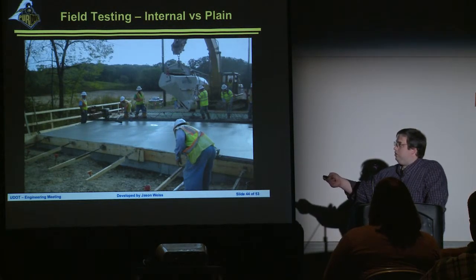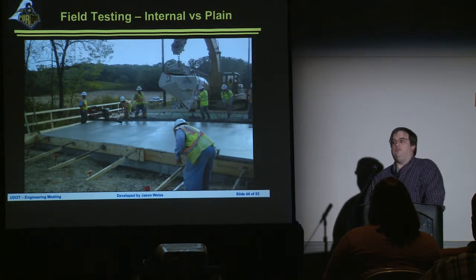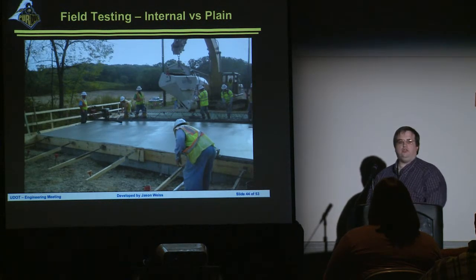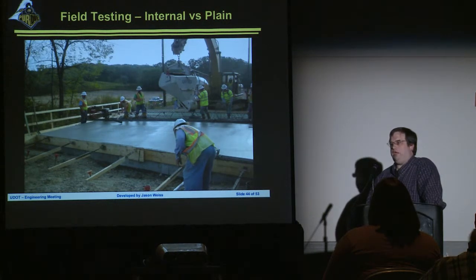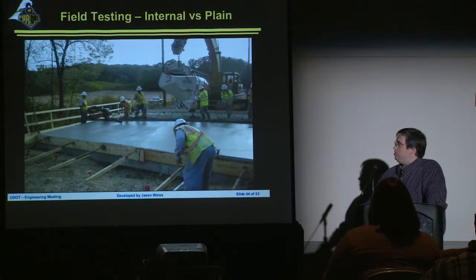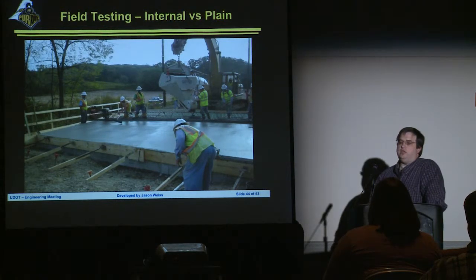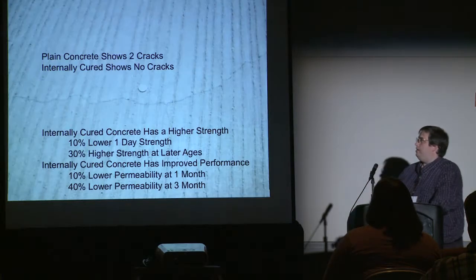This was a study that we had done in Indiana where I said I want to have two bridges that are next to each other because I want to cast a conventional mix and an internally cured mix back to back, and we want to evaluate their performance. So here's the internally cured one that's being cast. I will mention that early on we said we have to cast this with a bucket because we're worried about pumping it. That's no longer a concern. We're not worried at all about pumping it if the aggregates are properly pre-wetted.